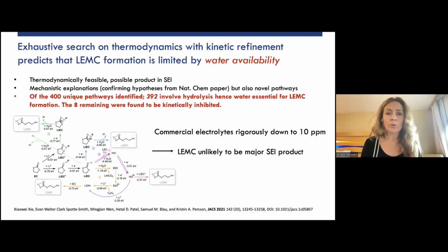Okay. So we found that, of course, LEMC is definitely a thermodynamically feasible product in the SEI. It's a downhill reaction. There's nothing keeping it from forming in that sense. As for mechanistic explanations, there were some hypothesized reactions in the Nature Chem paper, and we confirmed them. They are perfectly valid reactions. We also found some novel pathways, and some of them are shown down here.